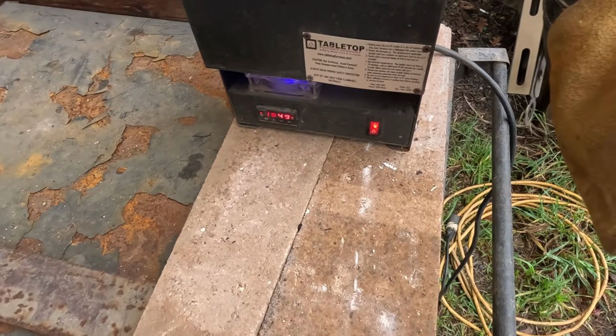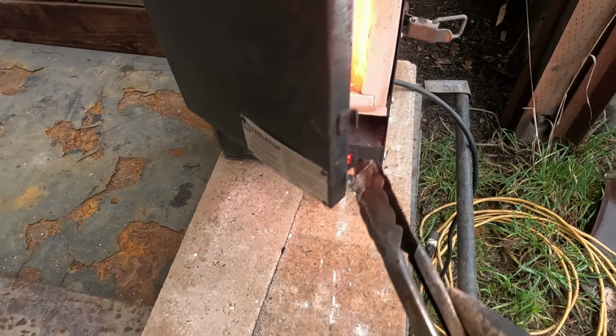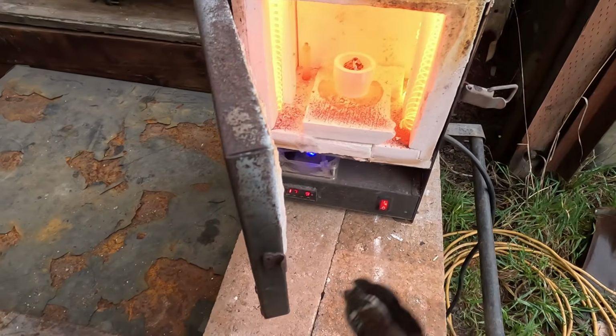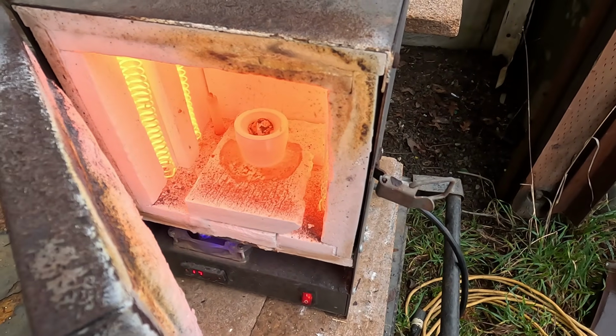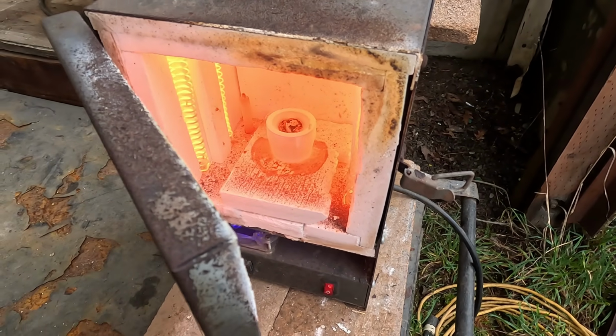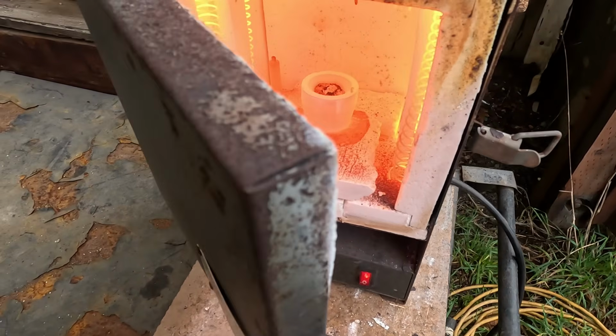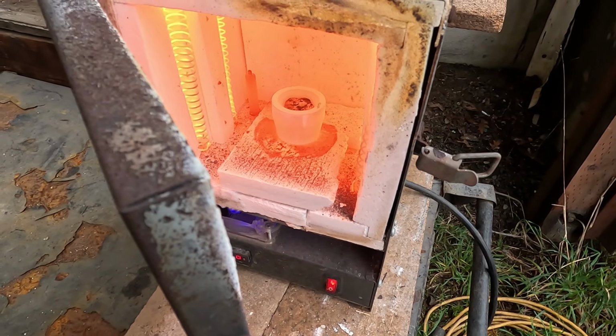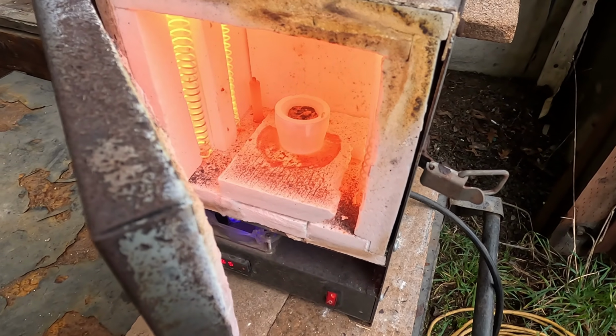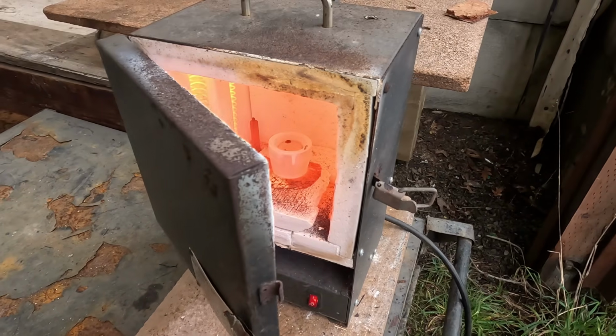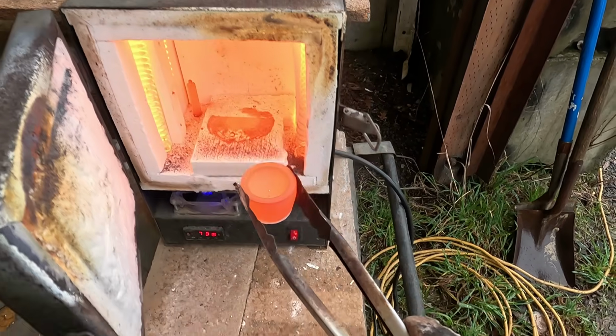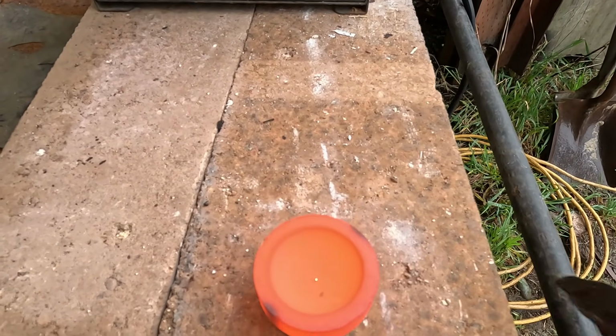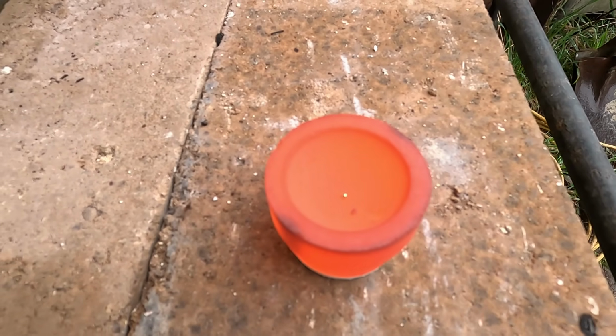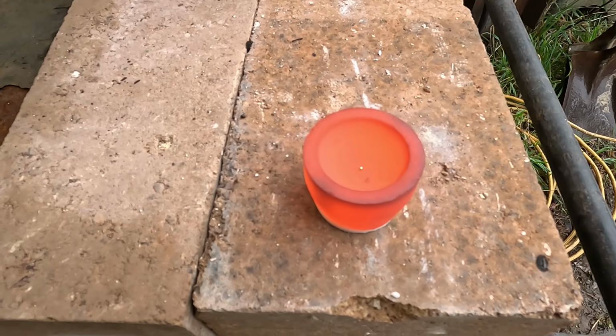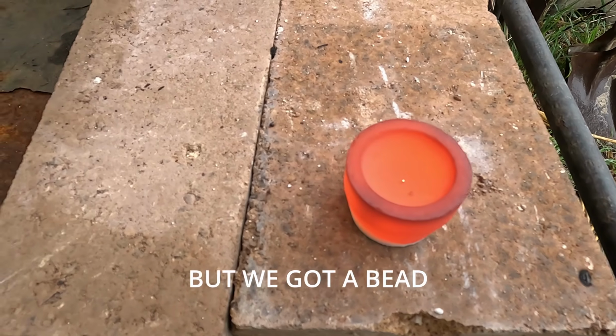Now as that bismuth melts, it'll start to oxidize, and the Cupel can absorb the oxides but not metals. So it's a sponge for oxides, and the precious metal bead will be left at the very end when all the base metals oxidize. It's a tiny bead. We got a bead.